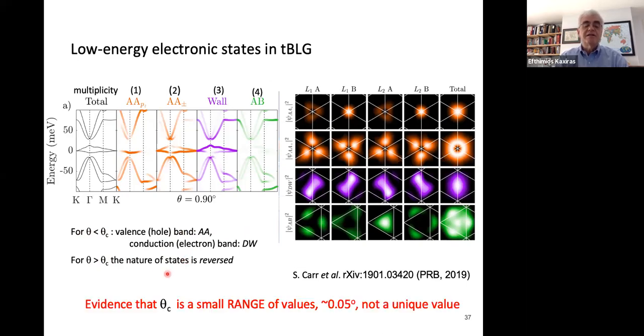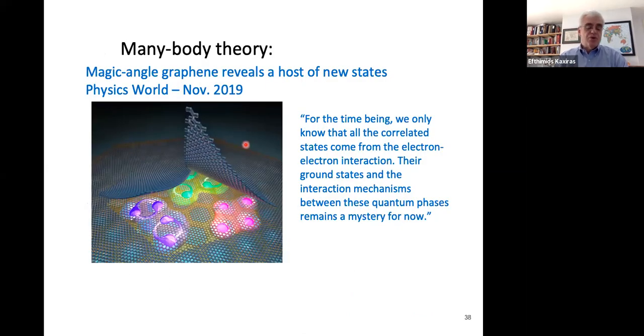Moreover, we have strong evidence that the critical value of the twist angle to produce all these interesting effects is not just one single unique value, but a small range of values of width about 0.05 degrees. And in fact, that makes a lot of sense, because if it were a single unique value, it would be very hard to hit that specific value in experiments. The fact that it's a range of values, roughly in the range that the experiment can manage to control the twist angle, makes it much more reasonable and feasible to hit that range of values where you have this very interesting behavior. So here's where we are. That's what we understand from single particle theory.